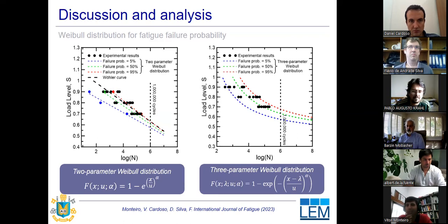However, more recent studies in fatigue life are already developing new methodologies to evaluate the fatigue life based on probabilistic methods. So for this research, I applied the Weibull distributions to study the fatigue life. Using the two-parameter and three-parameter Weibull distributions, we developed curves that are based on failure probability. So we can have the fatigue life based on a failure probability.